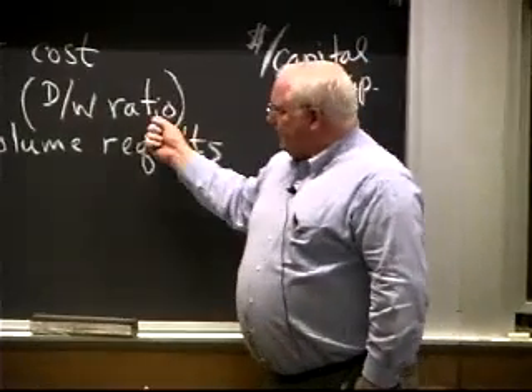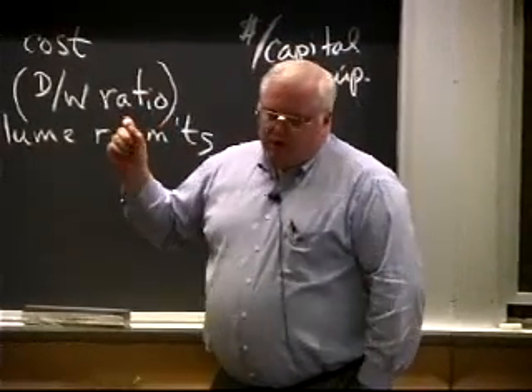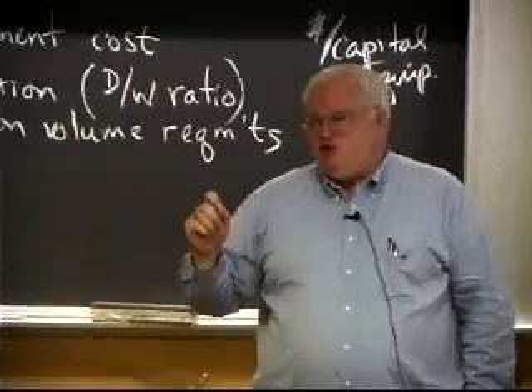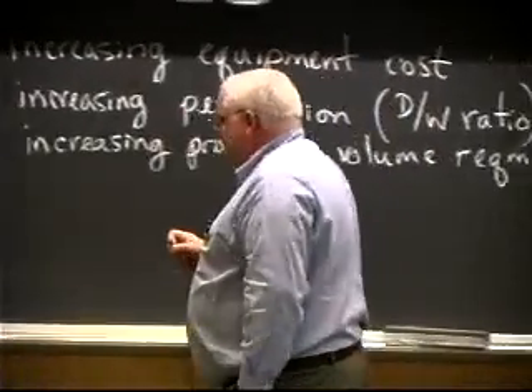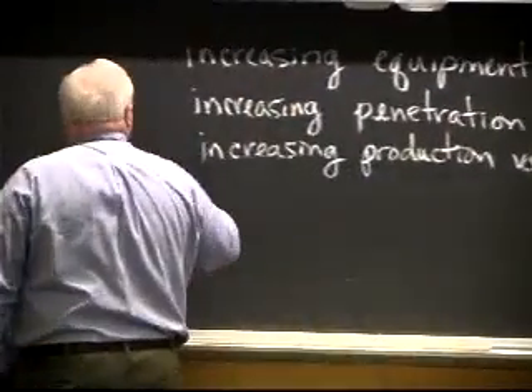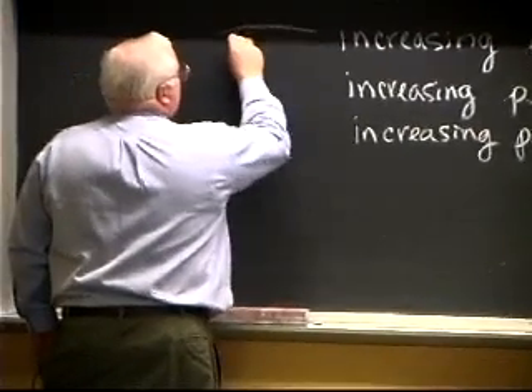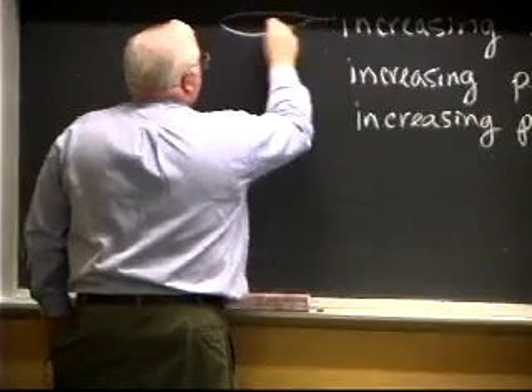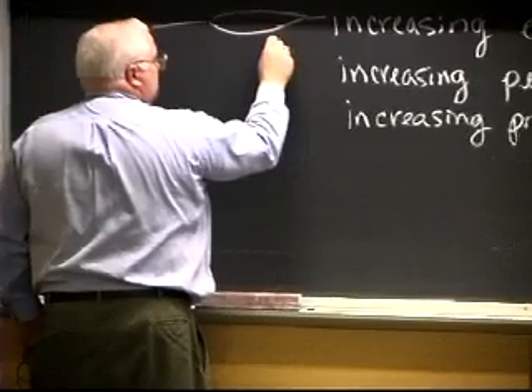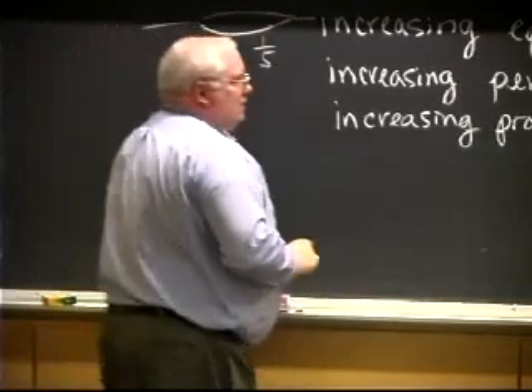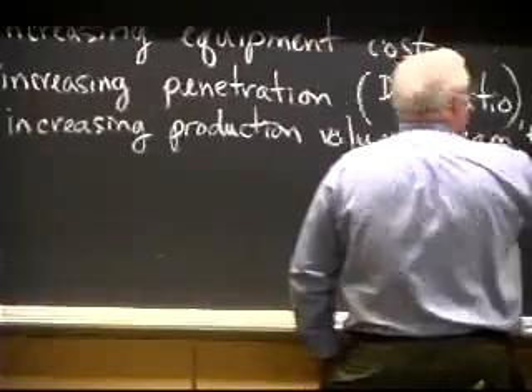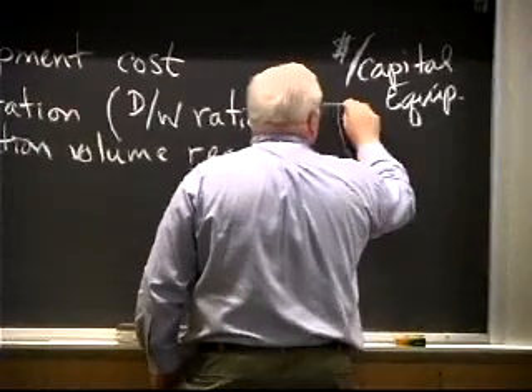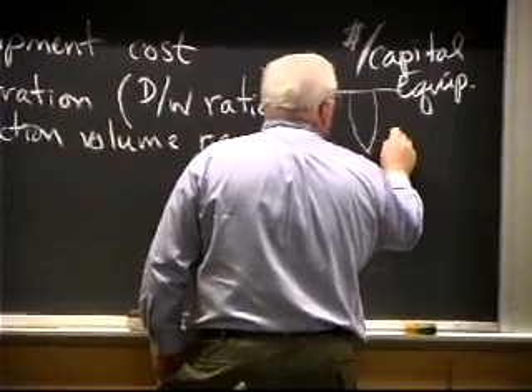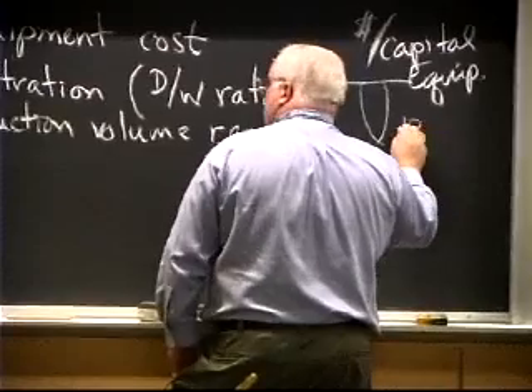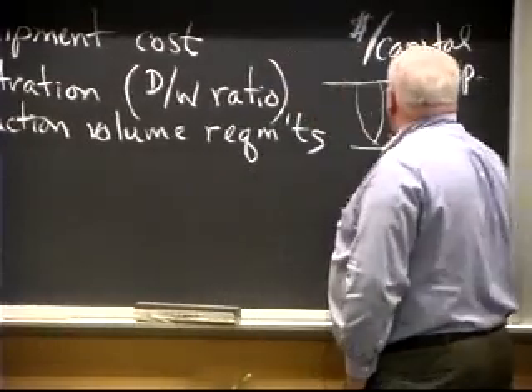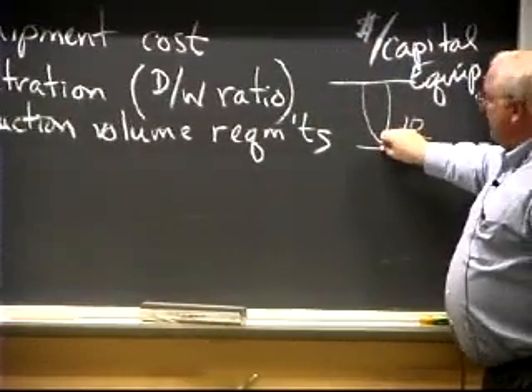But another thing that's important in all of this is the depth to width ratio of the weld pool, or the ability of the heat to penetrate and cause melting. Over here, you're going to have a weld pool on oxy-acetylene that might look like this. It might have a depth to width ratio of 1/5. And over here, you can have these holes that you drill, and typically you might get 10 to 1, 10 times as wide, or 10 times as deep as it is wide.